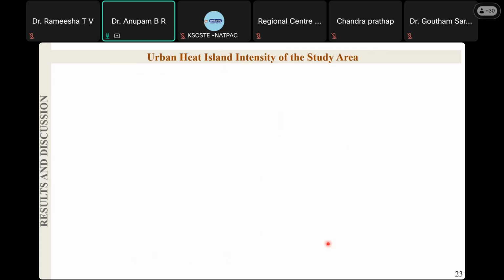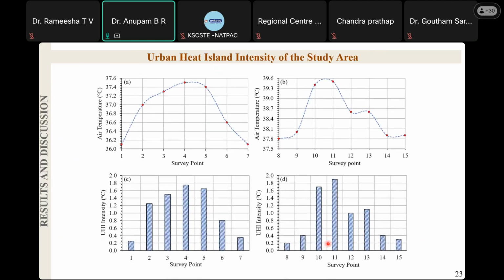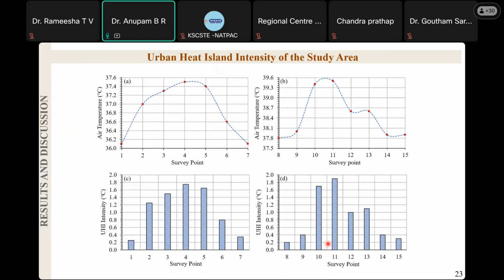So coming to the results, this was the urban heat island intensity result as a result of the vehicular surveys that we have conducted in Bhubaneswar city. You can see the UHI intensity of Bhubaneswar city was around 1.8 degrees Celsius. Meaning the city was almost 2 degrees Celsius hotter than its surrounding area on that particular day.